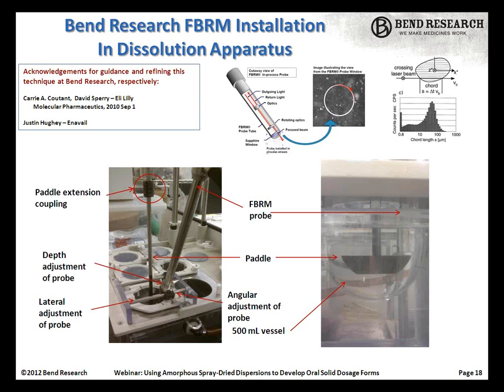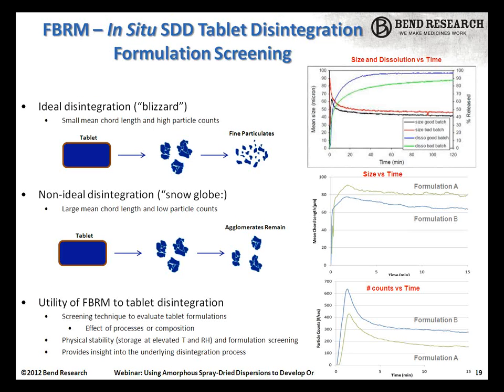So we do use an FBRM. Of course, FBRM measures what it gives us out of this is particle size versus time. And this shows our installation in a dissolution apparatus. We typically are not simultaneously measuring dissolution. This is just disintegration.